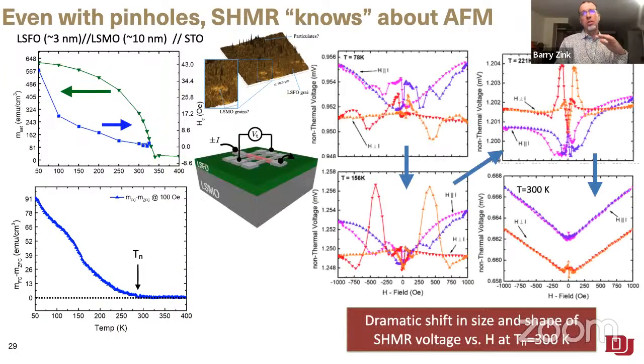There are more crazy things I could show you about how large these magnetoresistance signals get, but again, we're still working to understand this. In this particular sample, we have tied this change in the symmetry of the signal to something happening above the Néel temperature compared to below the Néel temperature. So it's promising, but again, there's more work we need to do.